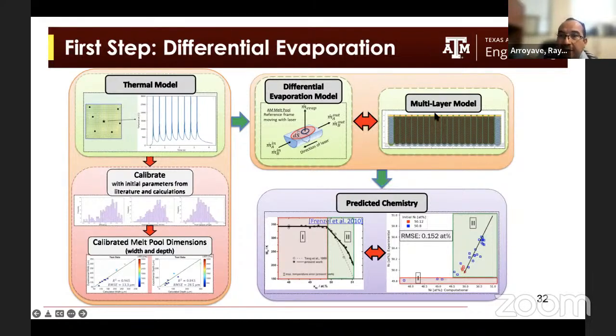Then, he built a multi-layer model that was able to integrate these single track predictions and took into account the mixing of chemistries as you build these layers successively. And he was able to demonstrate that at the end, he had a computational framework that was in very good agreement with experiments, right?